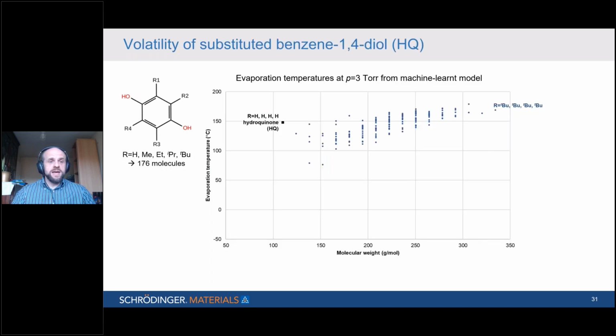So here are the results for benzene 1,4-diol. I've plotted the predicted temperature on the y-axis against molecular weight. And this is really just to spread out the data and give you an idea of the different data points that we have. There's 176 data points here. And as we change the R groups, obviously the molecular weight increases as you go from hydrogen all the way to tertiary butyl. And that's why there are these 20 or so vertical lines in the graph. So each point is a molecule with its predicted evaporation temperature.